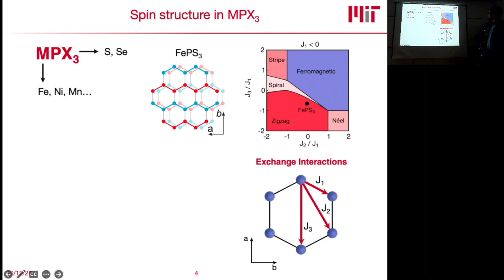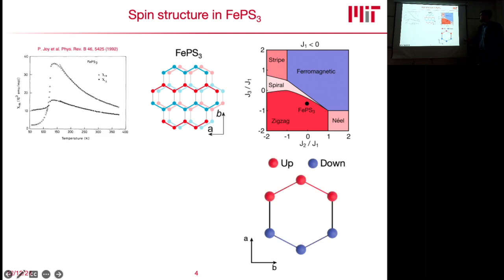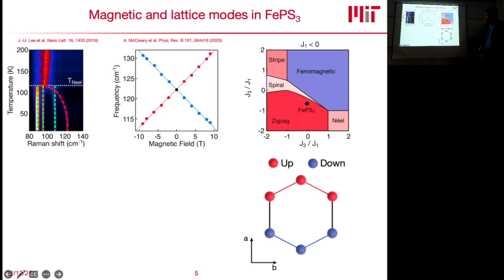And what we can already say is that, so this is a theoretical prediction over here, that this material is pretty close to a phase boundary. So this is usually something that means that your different states, the zigzag state, or for example then also the ferromagnetic states, are very close in energy, right? So that you just need to kind of nudge the sample and it will turn out to be a ferromagnet. This is at least the hope that we people in ultrafast physics usually have. And so what is also important in this material is that you have this strong anisotropy between out of plane and in plane directions, which then in turn leads to strong excitations in the terahertz region. So this is kind of number one. So this is for the light-matter coupling. We need excitations in the terahertz region that we can couple to actually control, to actually drive them to large amplitudes and control the ground state.